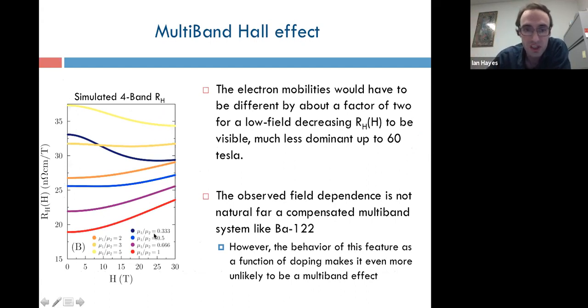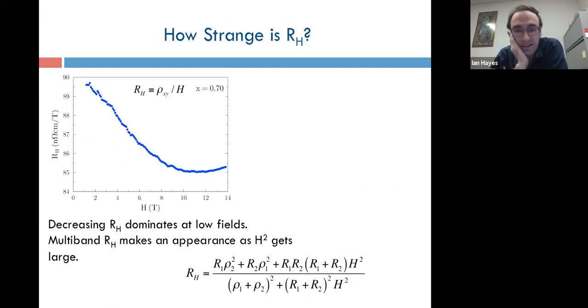You would need a sort of unrealistically large difference between the mobilities on the two electron sheets to get a low field decay in the Hall coefficient. And even then, it's not going to be very large. So this can't rule out multiband effects as the origin. There's a lot of effects one could layer on top of each other to get very complicated behaviors in the Hall coefficient. But it's at least not the natural thing in the first order calculation that you would do. And as I'll show you, what I'm calling the strange metal field dependence, where RH decreases with field, is confined only to very special parts of the phase diagram. All right, so back to data.